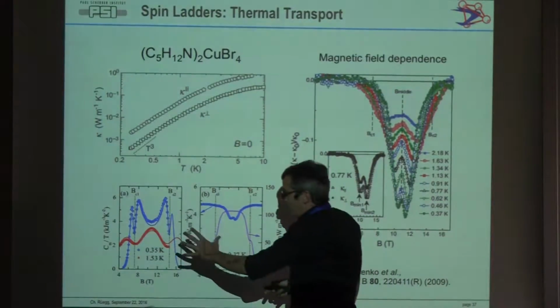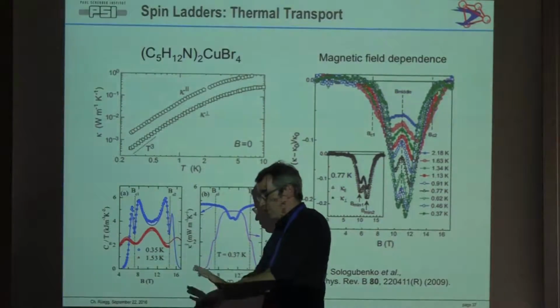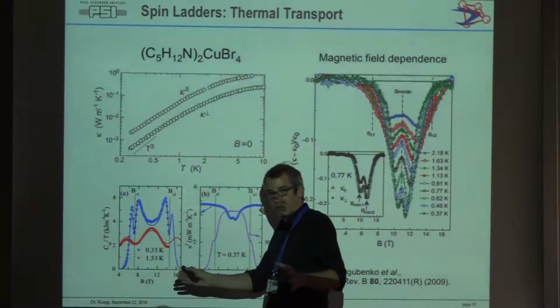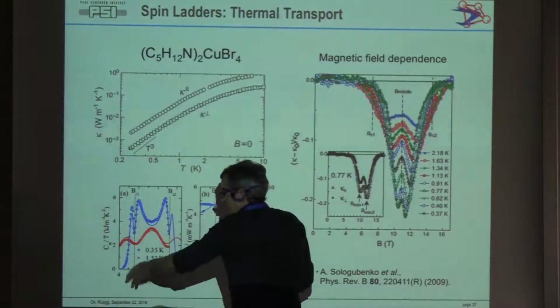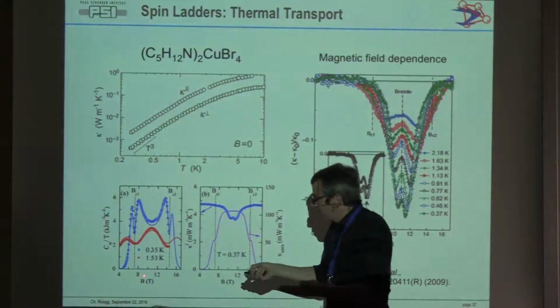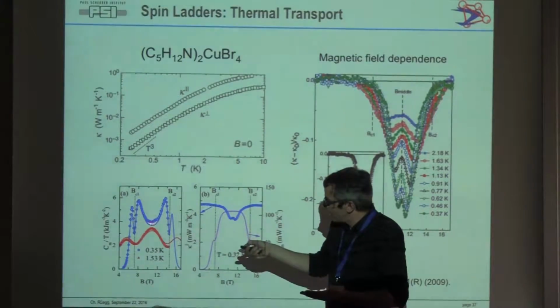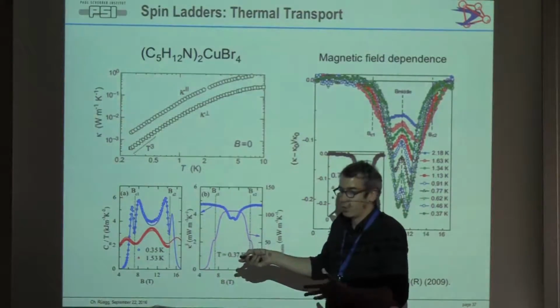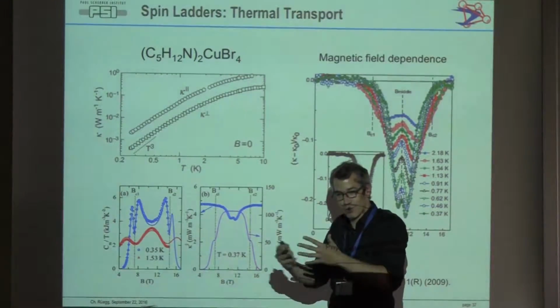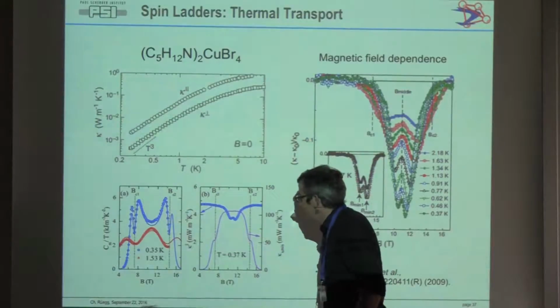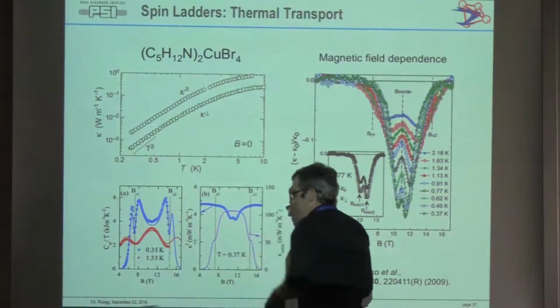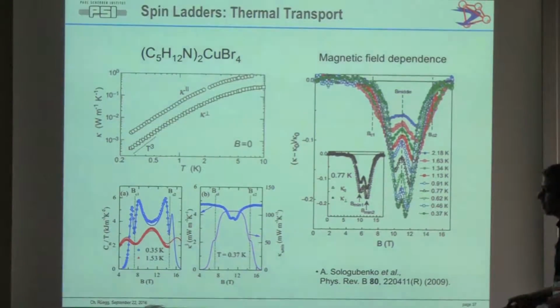So spinons are good in this system, low energy. You have these two lowest states, 1D, Luttinger liquid, everything fine. You can calculate, for example, specific heat as a function of temperature. That's the solid line. The points are the measurements. That's perfect agreement. So at low energies, your spinons do all your job. So you can calculate then what's the thermal conductivity you would expect for this system.